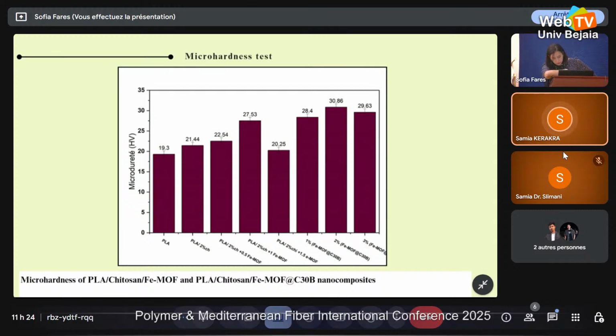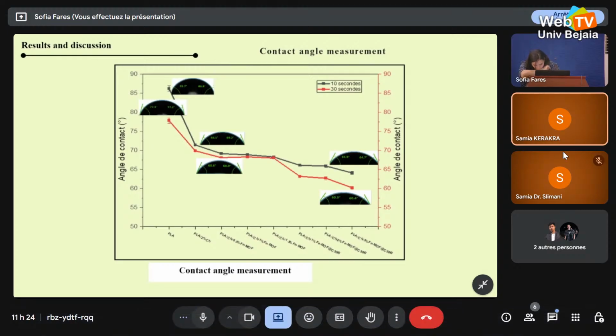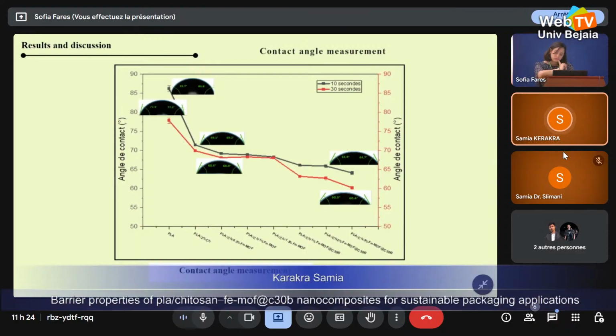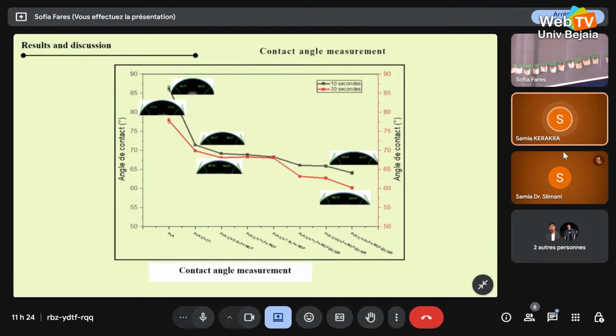Contact angle measurements. The change in contact angle of the films at 10 seconds and 30 seconds. And the results for PLA composites modified with 2% chitosan and incorporated fillers show significant change in surface wettability. The addition of chitosan reduced the contact angle, increasing hydrophilicity, and adding both fillers or the composites further reduces the contact angle, making the surface more hydrophilic.